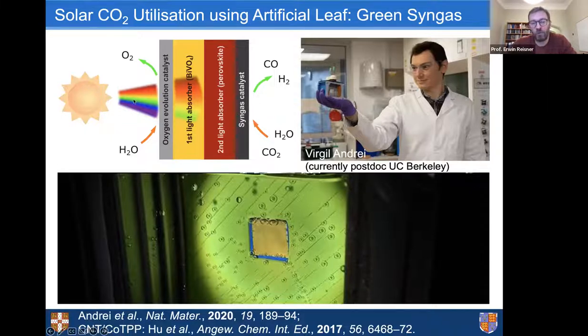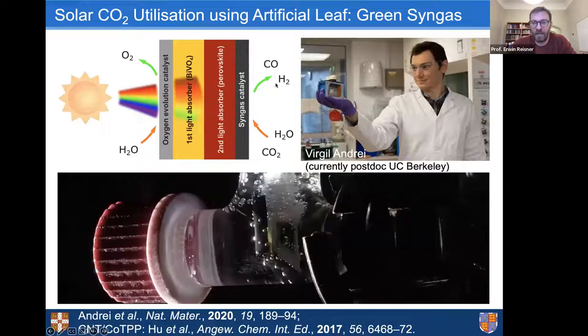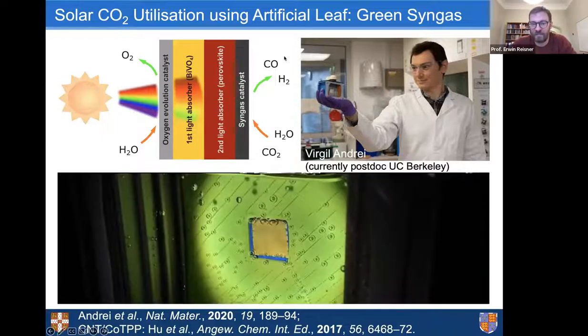So when we expose this to light, the UV and the blue are absorbed by the bismuth vanadate, and the rest of the visible spectrum by the perovskite, and this drives the conversion of CO2 and water to carbon monoxide and hydrogen. And this is known as syngas, this gas mixture here. And at the same time, the electrons are being sourced from water oxidation to oxygen.